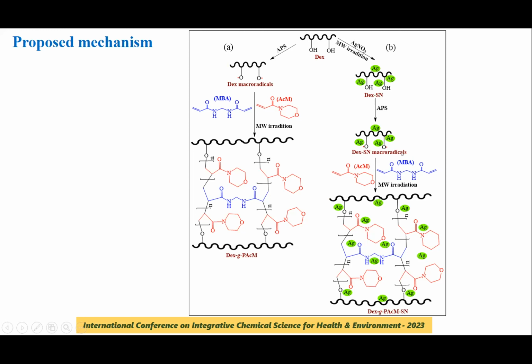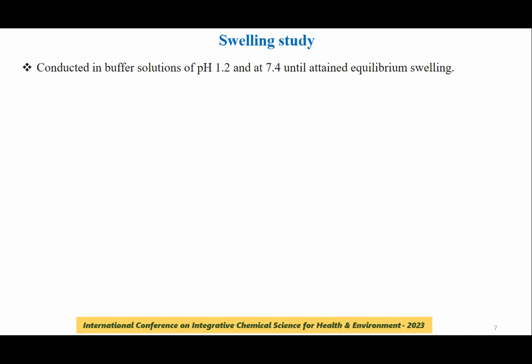And why have two irradiations been performed? Because the irradiation time for nanoparticle formation and for gel formation is different. To avoid degradation or loss of stability of the gel, we irradiate separately, because gel formation needs less time than nanoparticle formation. So the materials prepared were taken for swelling study at pH 1.2 and 7.4 until they attained equilibrium.